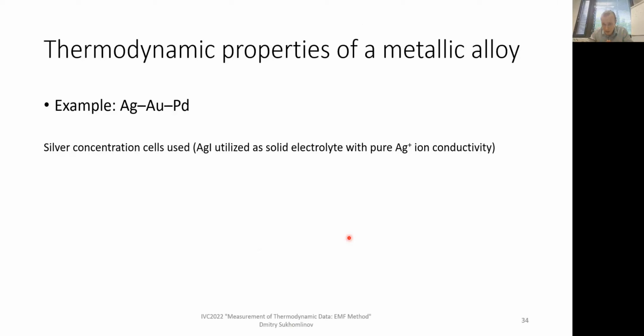And here, a different solid electrolyte was used, because our alloy contains silver and there are rather well-known super silver ion conductors available. One of them is silver iodide, and it was used. It is rather different stuff because temperatures are substantially lower compared to solid oxide electrolytes.